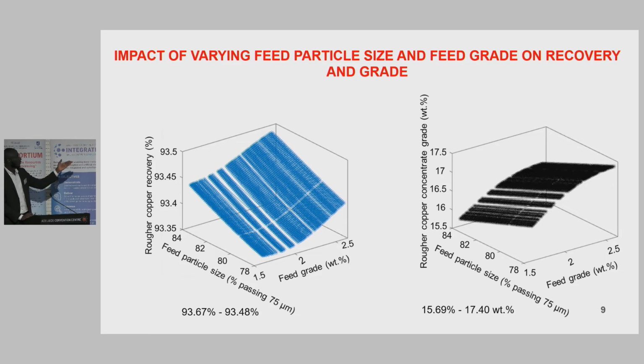So this work also wanted to ascertain the impact of feed grade and feed particle size on the optimum values that we have. Because in as much as we have optimum operating values for the various variables, for variables like feed grade and feed particle size, it's very difficult to keep them at a particular value. So we did a simulation where we varied feed grade and feed particle size simultaneously, but we kept all other variables at their optimum values as found by the various optimization algorithms. And from these results, we realized that if we go by this approach, we can have a near optimal recovery and grade with the values that we have at the moment.